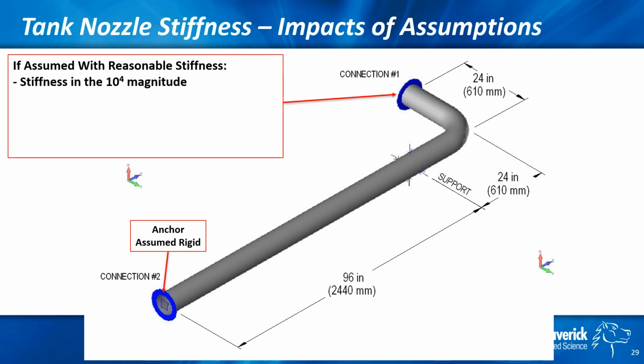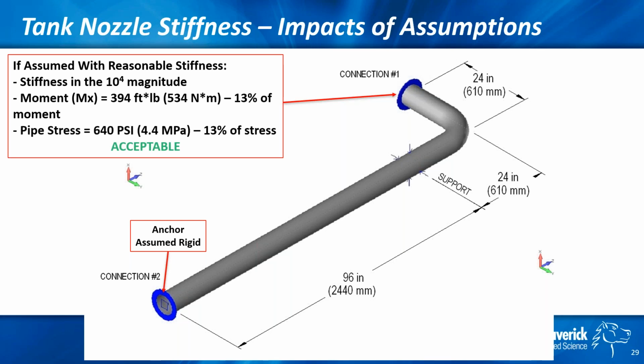If you assume a reasonable stiffness, now we've done studies on this. I'm not suggesting use 10 to the 4 across the board. Don't hear me say that. But usually 10 to the 4, 10 to the 5, 10 to the 6 gets in the reasonable magnitude for FRP. If you use a reasonable stiffness, your moment goes way down, your stress goes way down, about 8 times less, and I would say that's acceptable, all by using realistic assumptions.